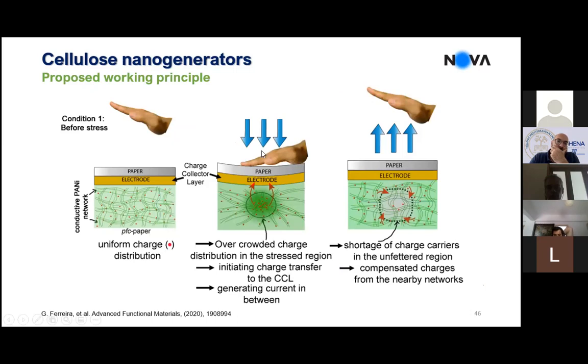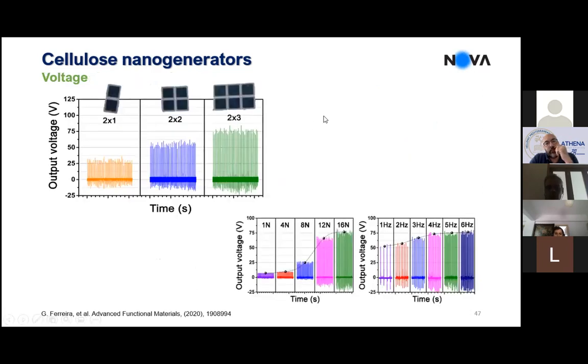Whenever you punch the structure, the mechanism that is proposed is a kind of charge transfer from the polymer to the electrode, due to the formation and local accumulation of charges under the mechanical deformation, that will promote the charge transfer to the electrode, and then the relaxation when you release the punch. You can play with the number of cells that you make in parallel or in series to also play with the voltage or the current that you can extract.